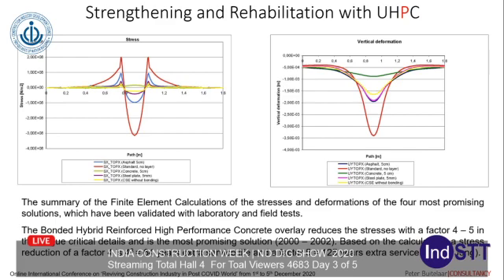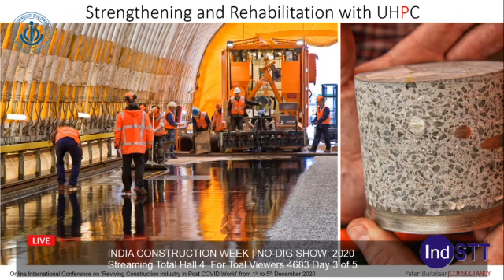To replace the existing wearing course with the hybrid reinforced UHPC overlay, the bond between the steel deck plate and the overlay is of crucial importance to secure total deck stiffness and a uniform monolithic behavior under all circumstances. For that reason, the first investigations were focused on creating a bonding zone that met all requirements. A bonding zone can easily be created by connecting the mesh reinforcement and the steel deck plate by welded studs, but this might result in local peak stresses and potentially new cracks.